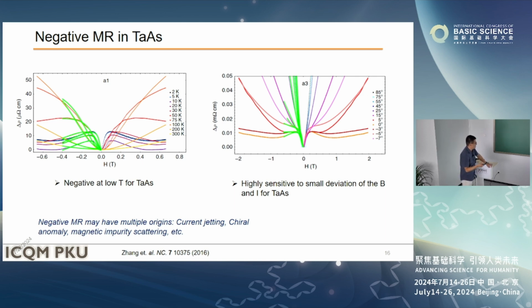And also, if you have some magnetic impurity, the magnetic field may align the moment of the impurity. So that at that point, it may suppress scattering of the electrons, and also give you a negative magnetoresistance. So to try to prove that what we observed is a chiral anomaly, we need to do something in experiment. So what we did,